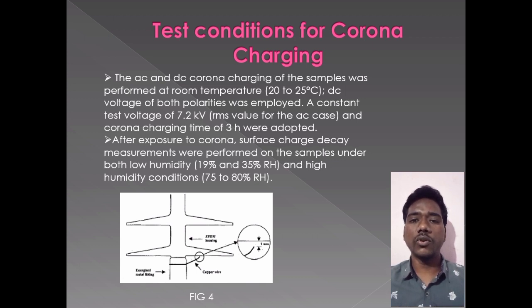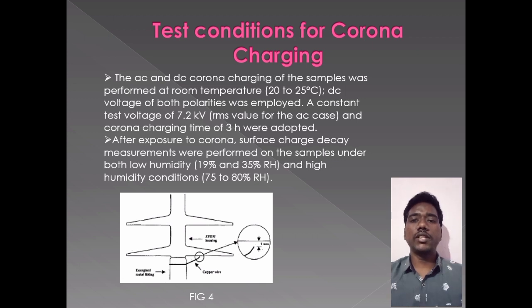After exposure to corona, surface charge decay measurements were performed on the samples under both low humidity and high humidity conditions. The measuring process continued until no appreciable charge magnitudes were detected. Correlation with expected field corona conditions.